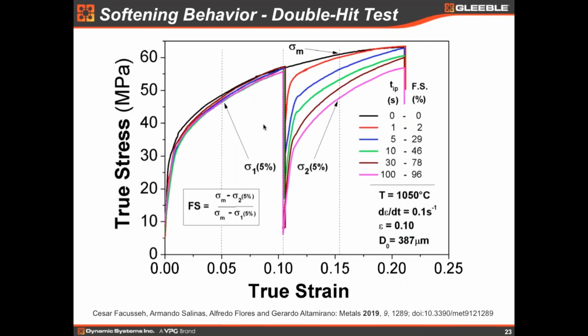So something that we can also evaluate is the softening between two deformations, or two passes if you're simulating a rolling schedule. So how do we do that? We have the stress strain curve, without interruption. This is the black line, and we can stop the first deformation at a certain point, wait for the interpass time, and then reload the specimen. If you don't do anything, we just continue the curve. So we follow this black line.